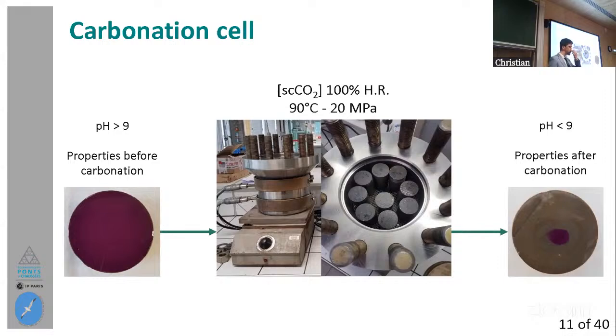Well, you wrote something about it, but you don't explain too much. Did you pay attention maybe to the history of pressure and temperature, whether alone they might affect the behavior of the sample? Well, this is a huge subject, actually. We were able to see that there are some changes in the specimens due to exposure to pressure, mainly the cement paste with the spheres, because of this issue of the spheres breaking, which was quite an issue to understand. And in terms of temperature, of course, we have some degradation due to temperature exposure, but we did not measure it on its own. We have done everything together in a coupled problem, and that was all.